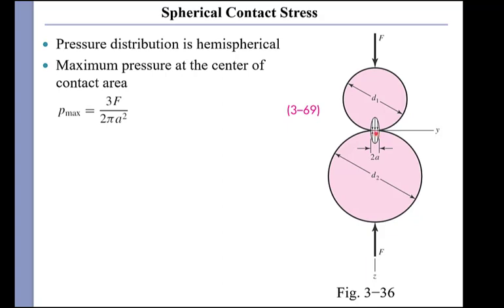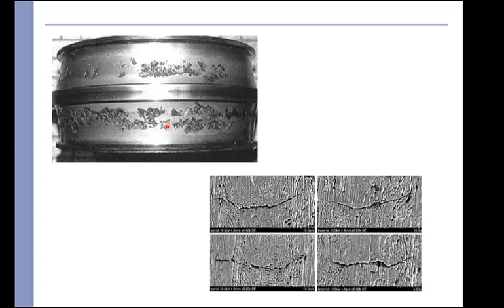Fatigue cracks initiate below the surface and then slowly make their way up to the surface. And that generates a bunch of spalls of material that fall off and generate pits in the material surface. These are some photographic images. This upper one is showing two races that ball bearings were rolling on. And over time, you get these pits that form that ruin the smooth rolling contact between the ball bearing and the race. And that's a failed bearing.